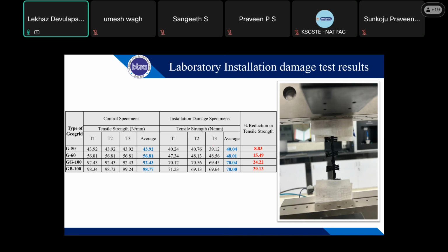After the installation test was done, we exhumed the specimens and did the tensile strength test. This is the average of 3 specimens, and these are the values. And this is the reduction. We can clearly see there was almost a 25 to 30% reduction for the glass grids. For the polyester grid, it was nearly a 10 to 15% reduction. So this shows that installation damage was clearly visible for the geogrids. When placing a geogrid, before the traffic comes, there is a reduction in strength.